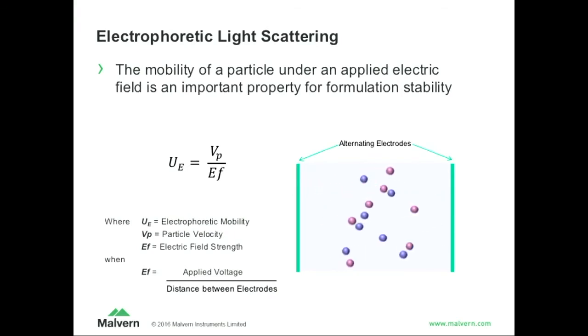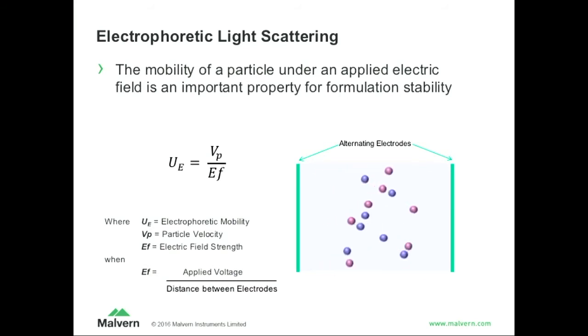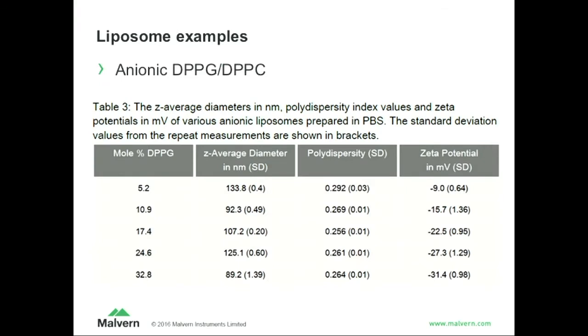One thing I'd like to briefly mention is that while you're doing the measurement you can also apply an electric field, and then particles of opposite charge will move in the electric field. So you can get what's called the zeta potential out of that by looking at the extra frequency shift — like a Doppler shift when a fire truck comes towards you or goes away from you. And let's look at some real liposome examples.